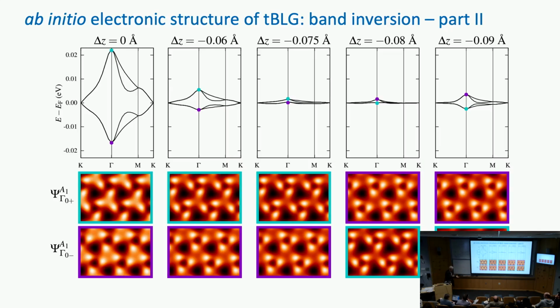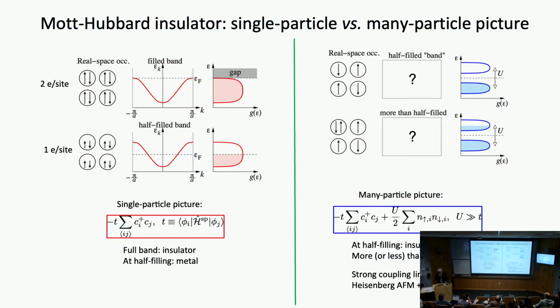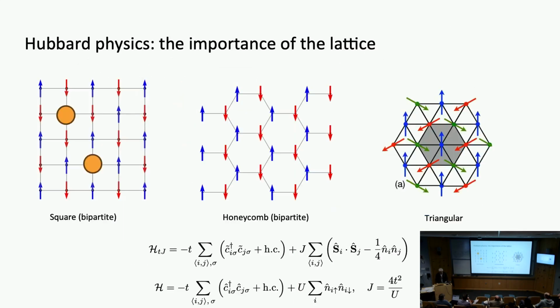And there are hints in experiment that this is indeed the case, because typically superconductivity is more pronounced for holes in these systems, but after a certain twist, superconductivity becomes more pronounced for electronic states. Which is equivalent to switching the character of electrons and holes in the system. So this is very exciting, and it's another example of what we are able to do. So very quickly, I want to sketch out what we are trying to do at the moment.